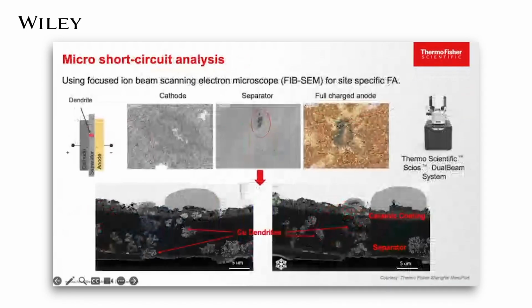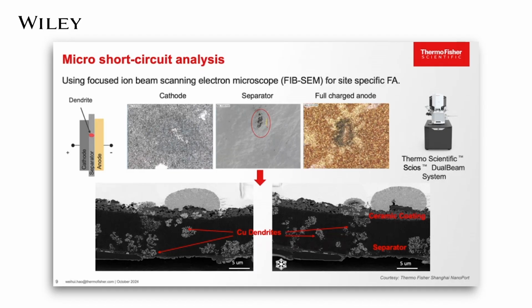If you look at this use case, micro short circuit in a lithium-ion battery always refers to localized failures that can significantly affect battery performance and safety. It can directly lead to fast self-discharging of the battery. It's a very common failure of lithium-ion batteries. Please see the schematic here. If copper particles are present in the cathode of a lithium-ion battery, then during charging and discharging cycles, the copper may experience dissolution, deposition and growth in the form of dendrites. Eventually, it will penetrate the separator and cause a short circuit or even thermal runaway.